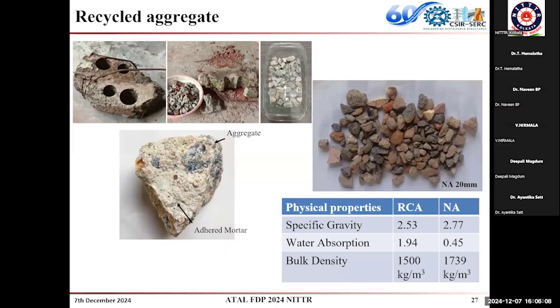Generally the interfacial transition zone is the weakest zone in the concrete. It creates problems like cracking. So when we use recycled aggregate with two interfacial transition zones, it further weakens the concrete. This is the disadvantage of using recycled aggregate.